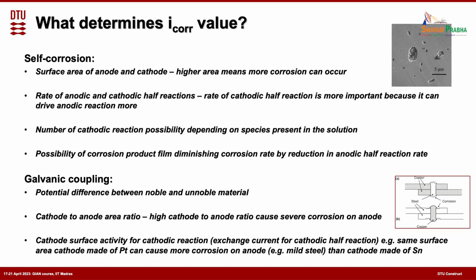Possibility of corrosion product film diminishing the corrosion rate. This is again what Lakshman mentioned as passivity, right? Sometimes the corrosion product film forms, and that makes some metals passive, and that also will reduce the corrosion. So that's also an important thing. We will see that because when we are using a passive metal, you can also make the metal stay in the passive region, and we can also use certain inhibitors for that.